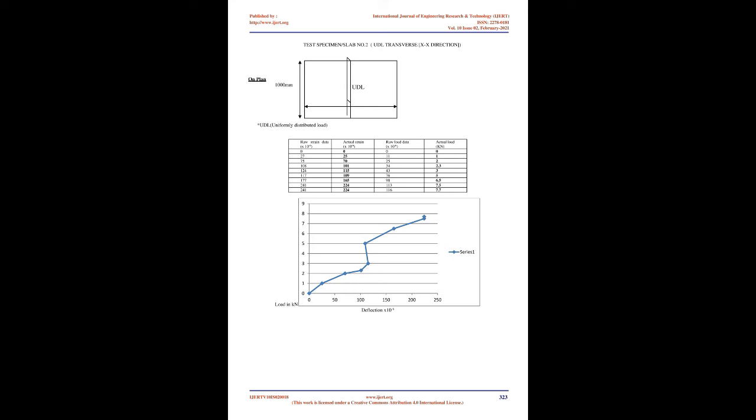The concrete was class 20 prepared in the laboratory, with batching done by weights. Concrete was placed in preformed formwork and compacted using a poker vibrator. The averaged compressive strengths of each type of concrete, tested according to ASTM C39, were found to be 13, 16.5, and 18 MPa, respectively. Figure 3.11 shows a schematic view and the picture of the test setup. Specimens were hoisted using the crane in the lab to the loading frame in the laboratory, and the whole assembly fitted with load cells, LVDT, and data logger electronic readout.